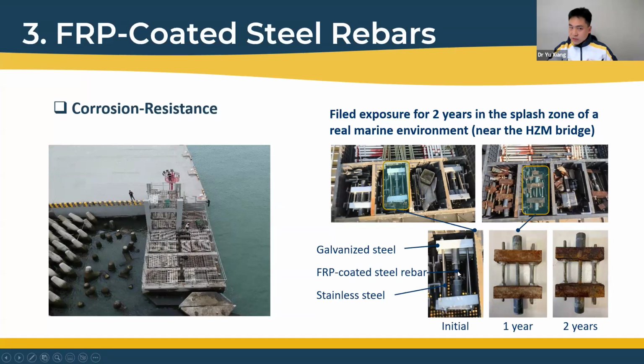This is the FRP coated steel rebar, used also to simulate its real stress state in service. The top and bottom profiles were made of galvanized steel, and the two screws were made of stainless steel, for a quick comparison during the exposure.